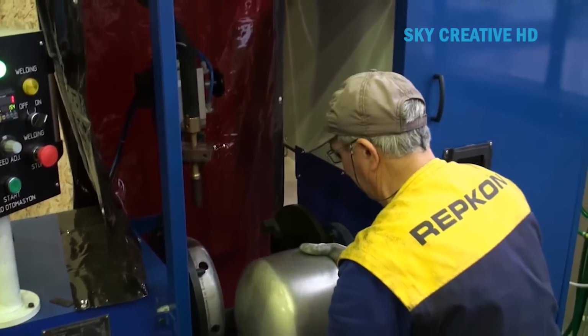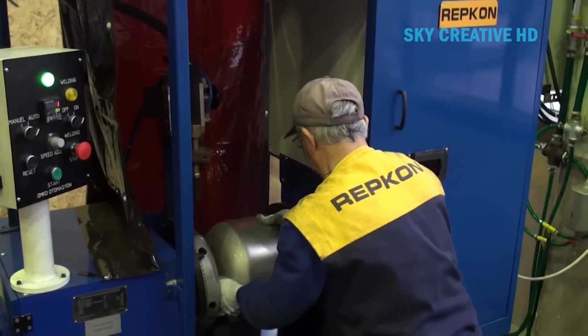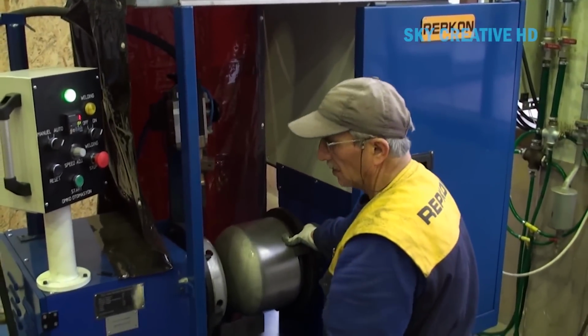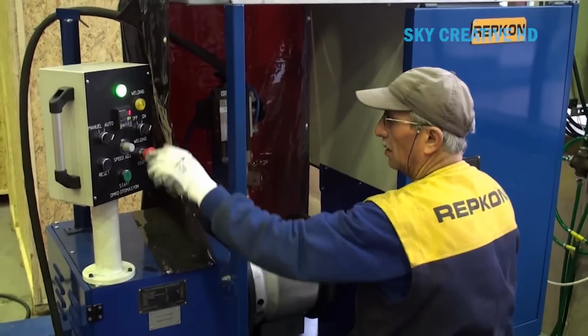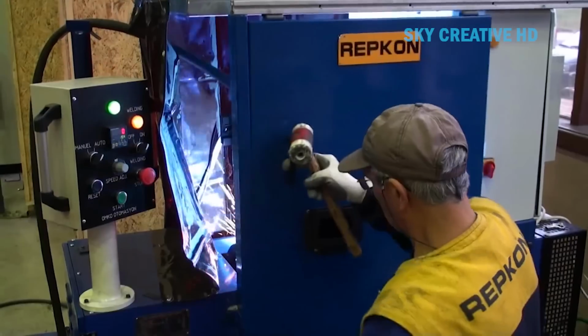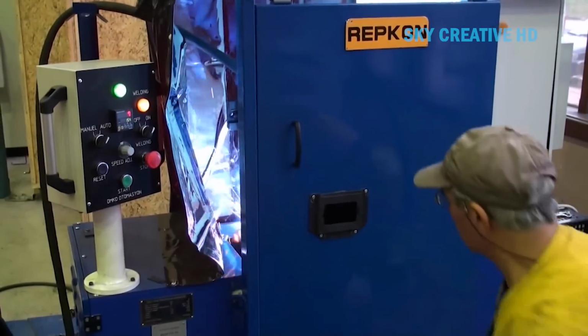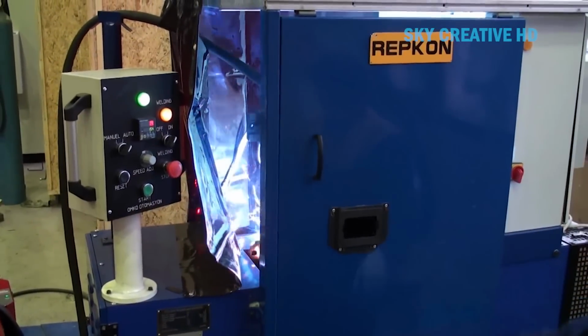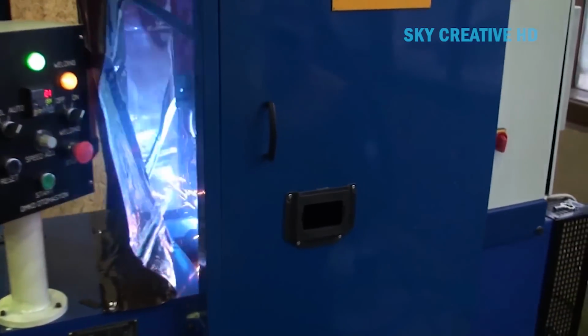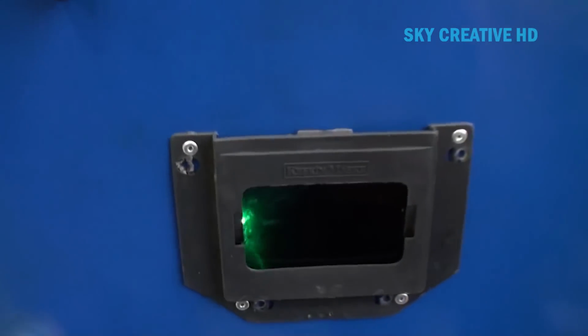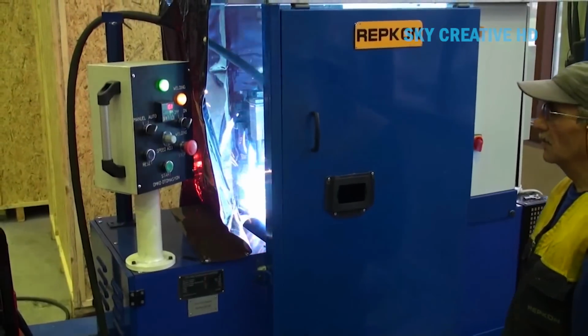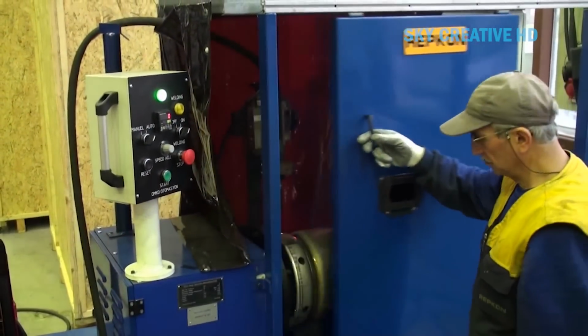In flow forming, a thick-walled preform is rotated at high speed and progressively formed over a mandrel by rollers. The rollers apply localized pressure, thinning the wall and extending the length of the cylinder to its final dimensions. This process significantly improves the material's strength and grain structure. Flow forming machines are highly specialized and require precise control over roller movements and forces.